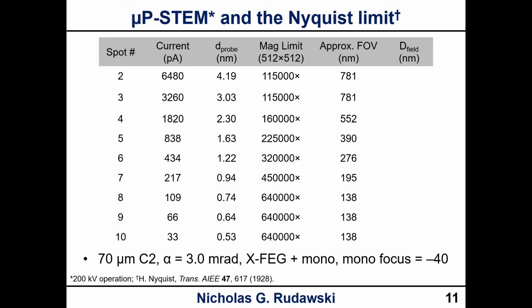And that of course has associated with it a field of view. So basically what this means is you would have to exceed this magnification before the probe size is limiting your detail. Okay? So if we look at, say, spot number 5, as long as we are at 225,000 X, which corresponds to a field of view of 390 nanometers, or less, we are not limited by the size of the probe in terms of the detail that we can see. Okay. And then we can figure out pixel size and we know alpha.